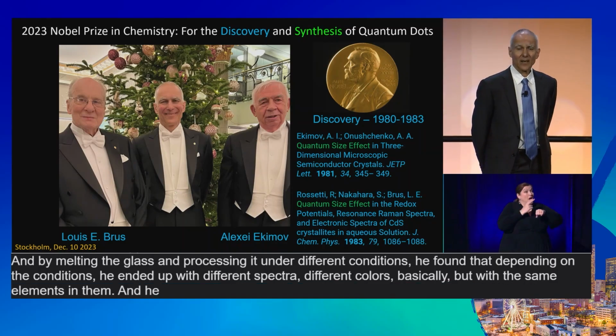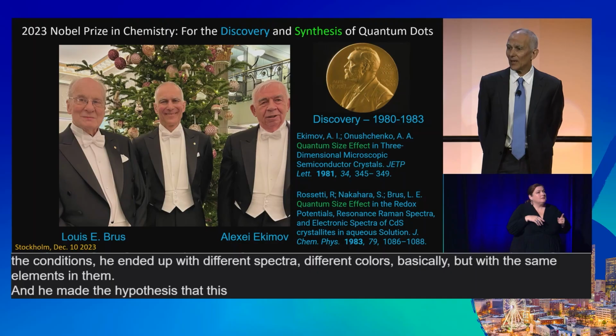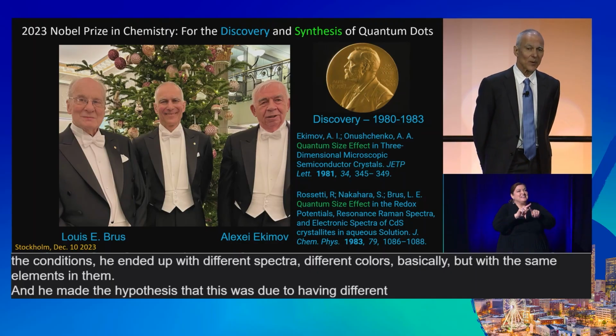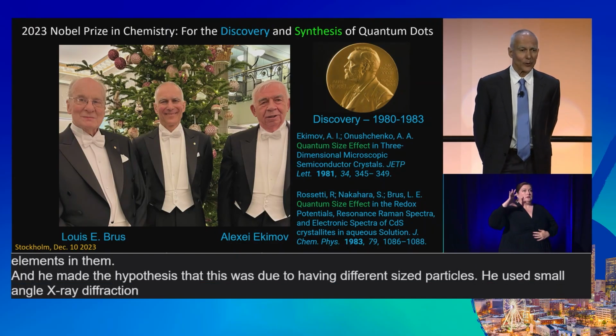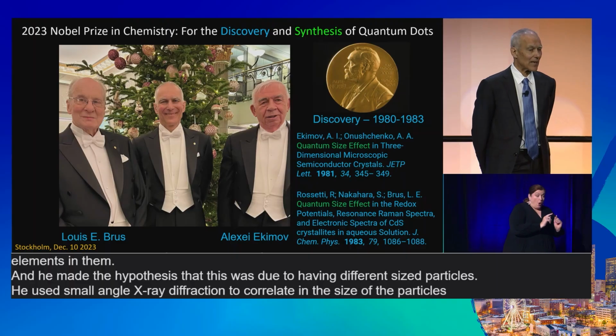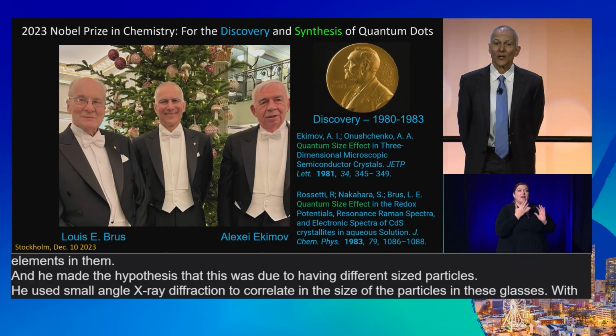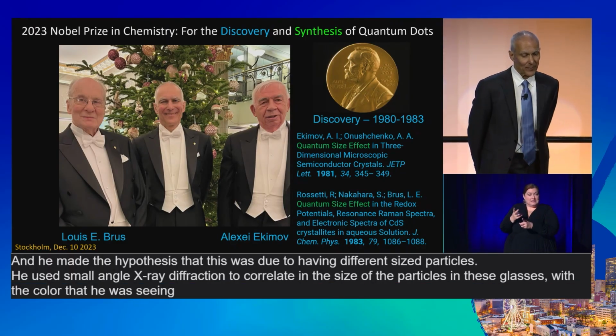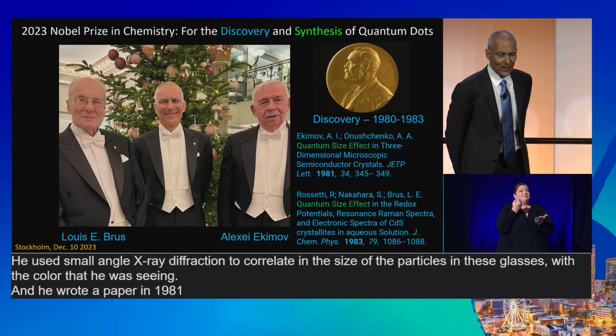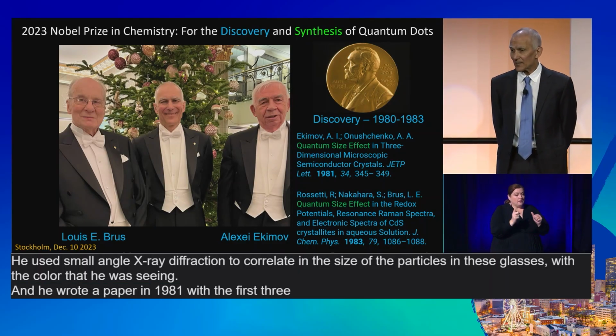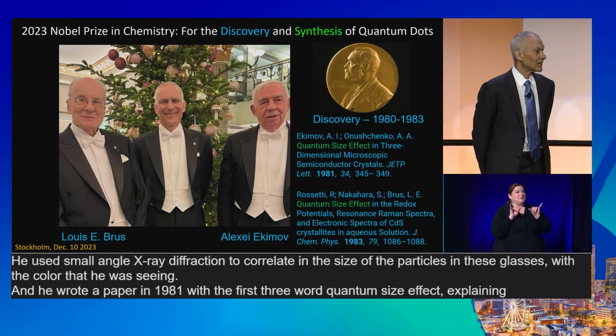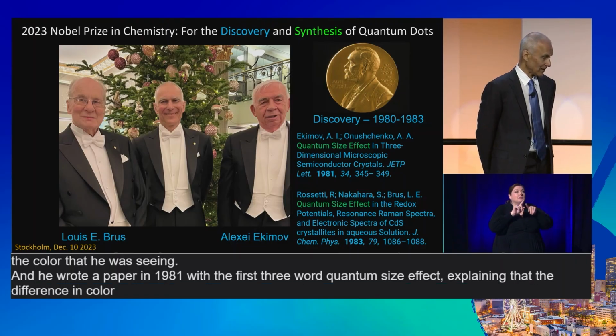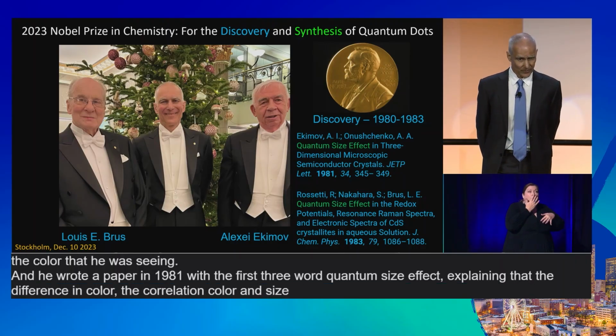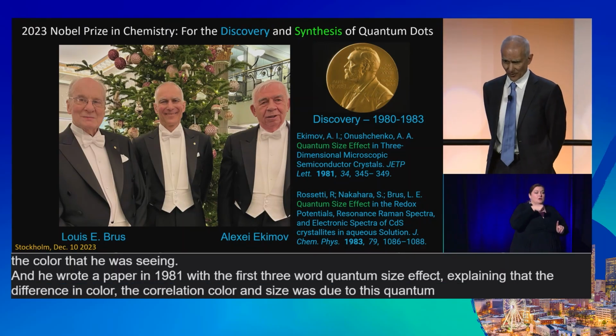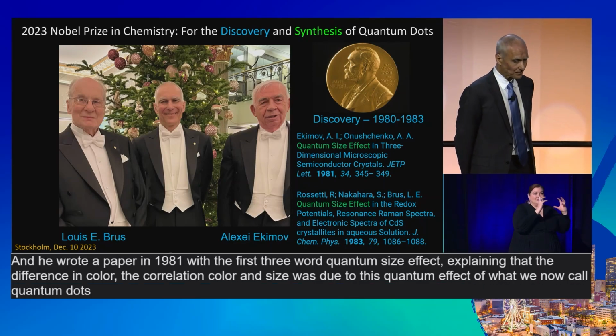And he made the hypothesis that this was due to having different sized particles. He used small angle X-ray diffraction to correlate the size of the particles in these glasses with the color that he was seeing. And he wrote a paper in 1981 with the first three words, quantum size effect, explaining that the correlation in color and size was due to this quantum effect of what we now call quantum dots.